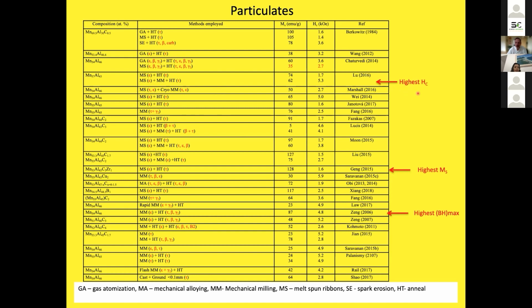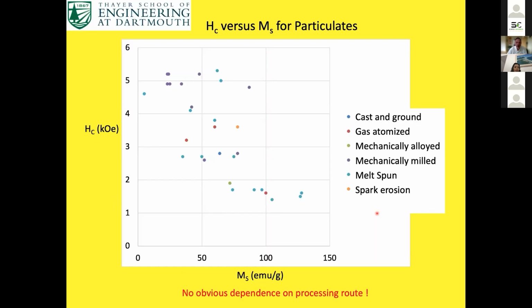the people who've got the highest coercivity are not the same as those who've got the highest saturation magnetization, and are not the same as those results from the highest energy product. In fact, the highest energy product for particulates was obtained by my group in 2006, and I think it's still probably the highest. This graph replots that data as the coercivity as a function of saturation magnetization, and the color